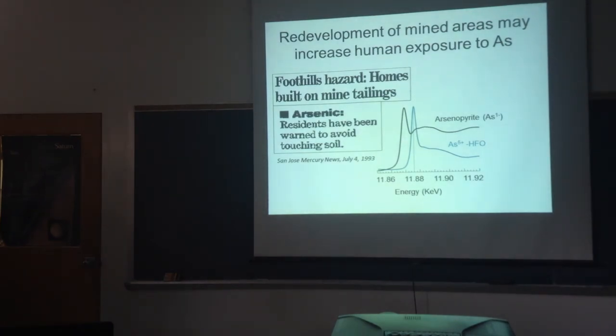One of the pieces of research that was done back then by some of my USGS colleagues had to do with what form the arsenic is in. They used the synchrotron radiation at the Stanford light source, the SSRL, and it's a nice way to tell the form of arsenic. You get a peak shift if the arsenic is in the minus one oxidation state of arsenopyrite, you see the black line, and if it's in the arsenate or plus five state associated here with hydrous ferric oxides, you get a very distinct shift to the plus five. And so it turns out that the plus five is more bioavailable than the minus one.